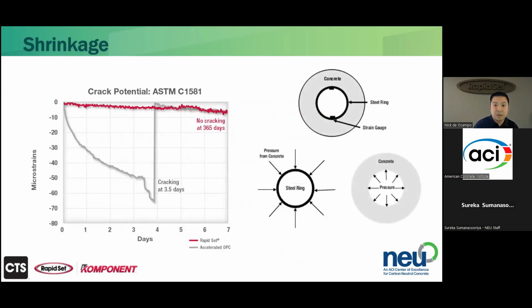This is another type of shrinkage test we call the ring test, ASTM C1581. Rather than having an unrestrained bar, like in ASTM C157, which is great for quantifying the amount of shrinkage, here we're testing basically how long it's going to take for a material to crack, because we know that all concretes will shrink.